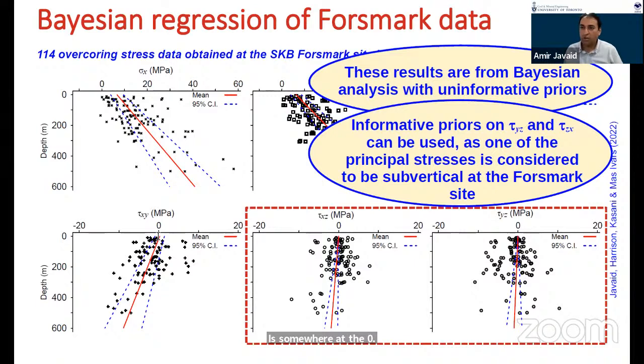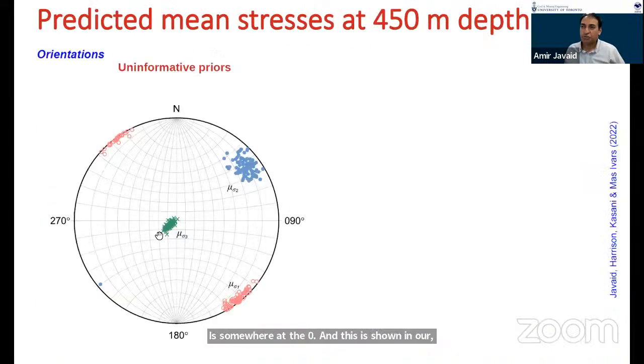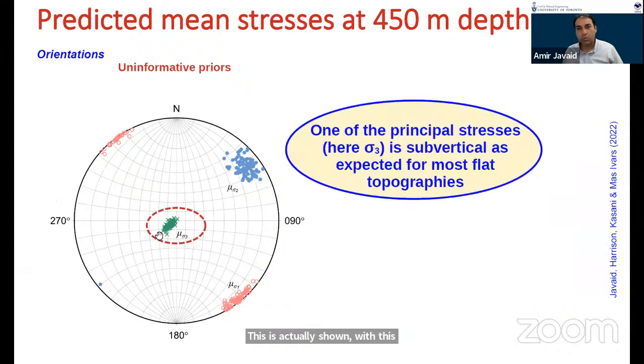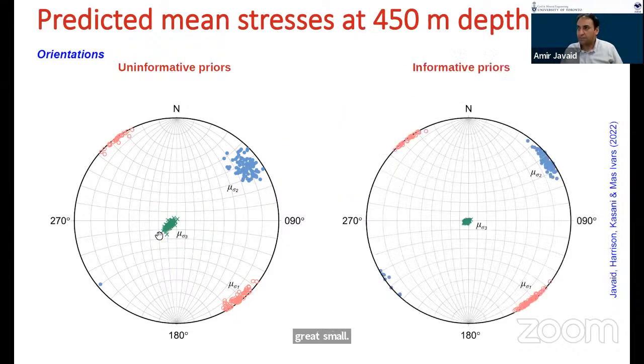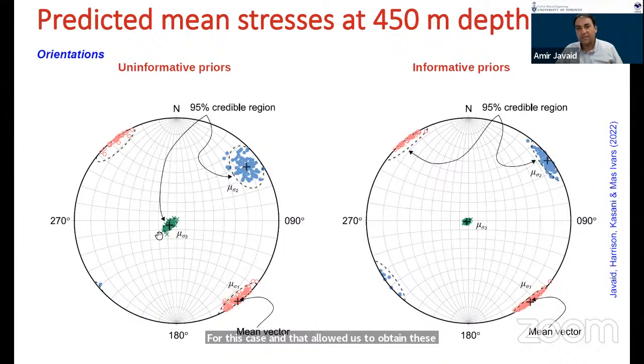And this is shown in the results we were discussing. This is actually shown with this uninformative analysis as well, that one of the principal stresses is subvertical. So what I have done in the informative priors is use a very tight probability distribution on tau xy, tau xz and tau yz, the two vertical shear components. These are very tight probability distributions, with a mean of 0 and a very small standard deviation. That allowed us to obtain better estimates, with a clearly significant reduction of variability in all these stress components. I hope this answers your question.